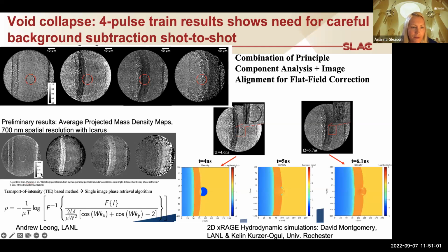But it's tough, right? We're having some normalization issues here. We've got some negative values. So we can't directly pull density off of here yet, but it's possible. This is also for a single phase. So a single material is where this approach works really well. And here we've got 2 different starting materials, the silica wall and the surrounding SU8. But this is preliminary analysis, and it shows that we're able to march forward sequentially.